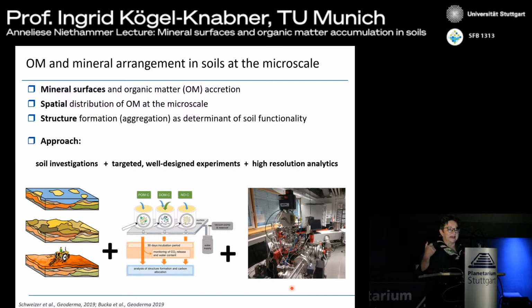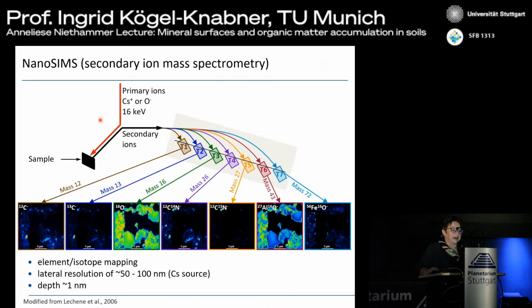This is our NanoSIMS. NanoSIMS is secondary ion mass spectrometry at the nanoscale, and I will explain shortly because I will show a lot of such NanoSIMS data. What you do is you hit a surface, and the surface has to be very, very flat, with primary ions. In our case, it's most of the time cesium, and when you hit the sample surface, you sputter off so-called secondary ions.